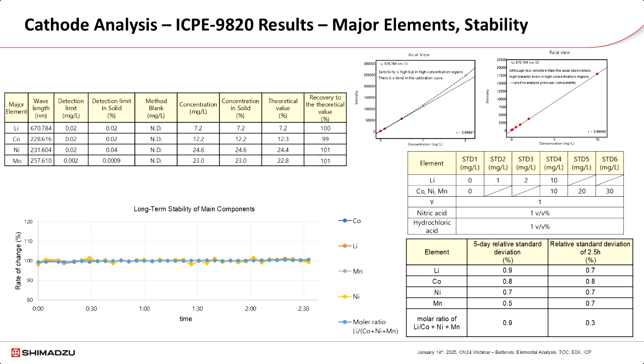Once the best wavelengths are selected for each element, it's important to also ensure the stability of the system over long periods of time, because many of the elements in cathode samples are in high concentration. Salt buildup of various components of the ICP can cause signal instability. Here, we demonstrate robustness of the system over a 2.5-hour period, as shown in the lower left figure, and the small relative standard deviation of the measurement taken over 5 days, as shown in the lower right table.